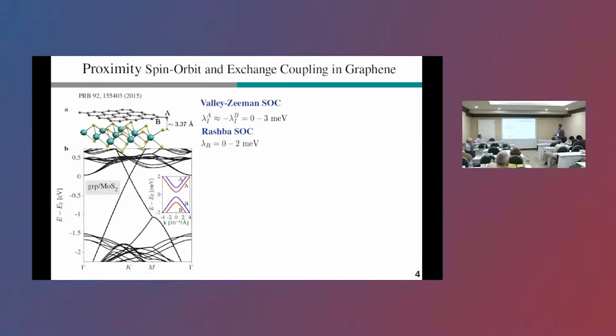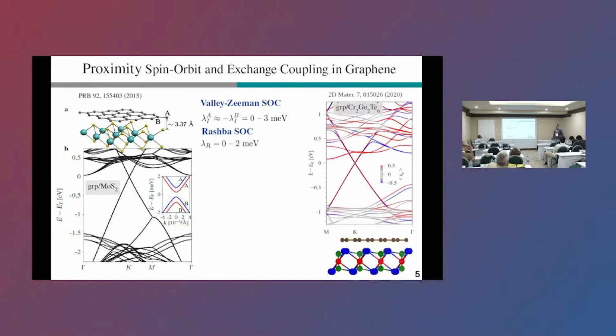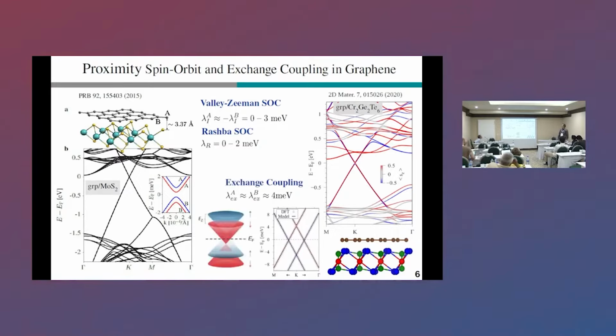Now, another spin interaction that can be induced in graphene is, of course, the exchange coupling. So, when you place graphene on chromium germanium telluride, for example, which is a ferromagnetic semiconductor, you will find a very similar situation. The Dirac states of graphene are quite nicely preserved within the band gap, and if you then zoom in to the Dirac states, you will find such a splitting of the bands, which reminds us of the Zeeman splitting from an external magnetic field. But here it is not an external magnetic field, it's rather the exchange field originating from the ferromagnetic semiconductor.